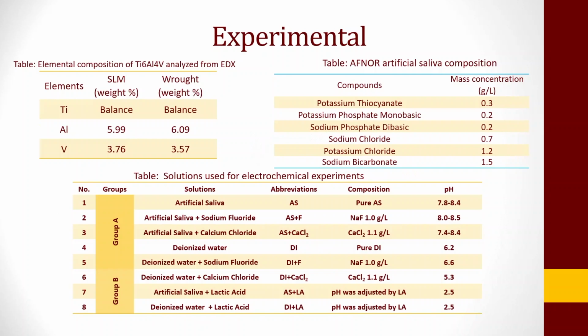So before I jump into the results, I quickly want to show you that using the EDS, we have found the compositions of SLM, or selectively laser melted, and the wrought. They are pretty much the same, and we have used the artificial saliva, and here's the composition of the artificial saliva shown in the upper table on the right.